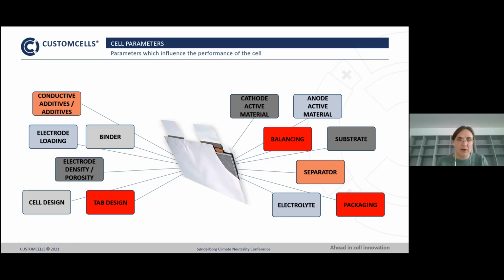Furthermore, there are some concepts that go into this design of a battery. The overall cell design, so what shape does it have, how does it look, but also things like balancing between anode and cathode. So the anode is always not only physically larger, but also a little bit larger from a capacity standpoint, to make sure that every lithium ion can be incorporated into the anode. Furthermore, concepts like electrode loading, so how thick is the layer of active material on the substrate, and electrode density and porosity will have a high influence on the characteristic of the battery cell.